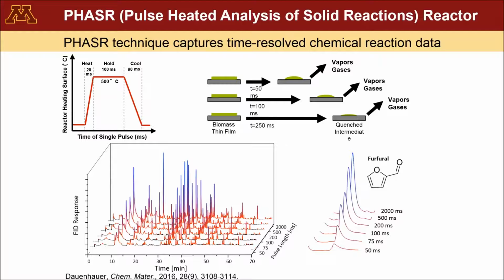For example, here is some of the data which we obtained from the Phasr reactor. We kept the sample at 500 C for 50 milliseconds. Then we quench the reaction, and then we analyze the product. Also, we repeat this experiment for different pulse times: 75 milliseconds, 100 milliseconds, 200 milliseconds, 500 milliseconds, and 2 seconds. After doing this experiment, we can use mass spec to identify each peak, and then we can plot it separately. For example, this is one of the peaks, which is furfural, and we see what's happening for each individual product with time during the pyrolysis of, for example, biomass or plastic.